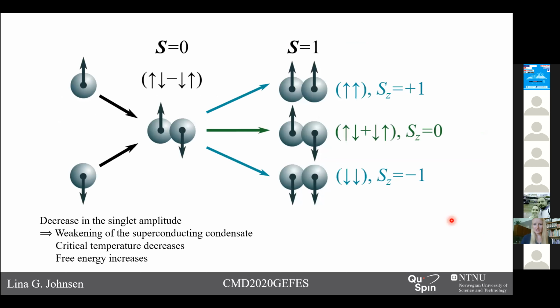So why would we expect this? Well, in conventional superconductors, electrons form singlet Cooper pairs, and this singlet Cooper pair amplitude is proportional to the superconducting condensation energy in the superconducting gap. And therefore, a decrease in the singlet amplitude leads to a weakening of the superconducting condensate, and therefore also a decrease in the critical temperature and an increase in the free energy of the system. And since the minimum of the free energy is the ground state of the system, we can use the free energy to find which magnetization direction is preferred.